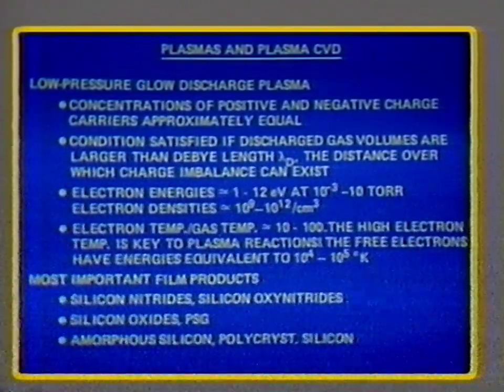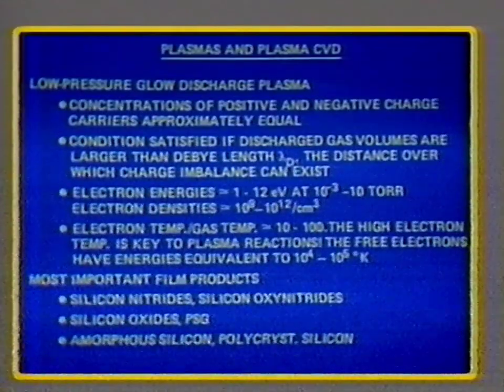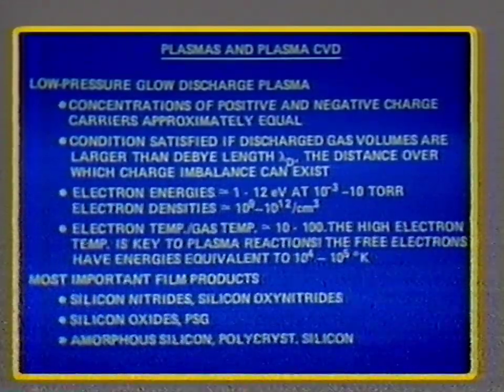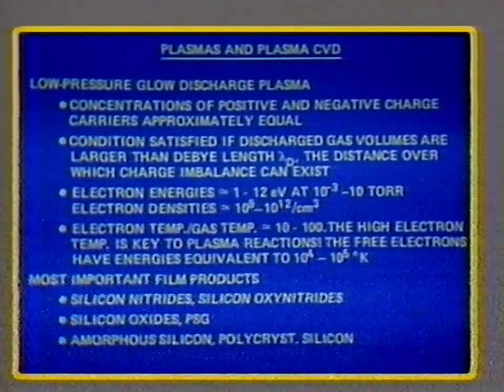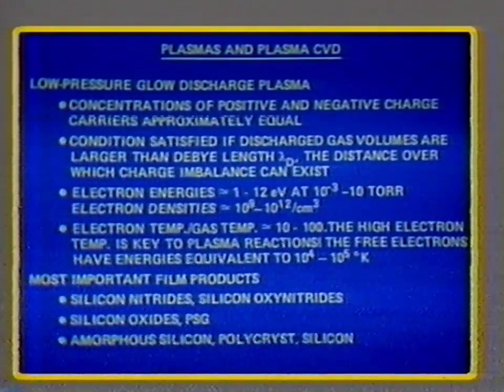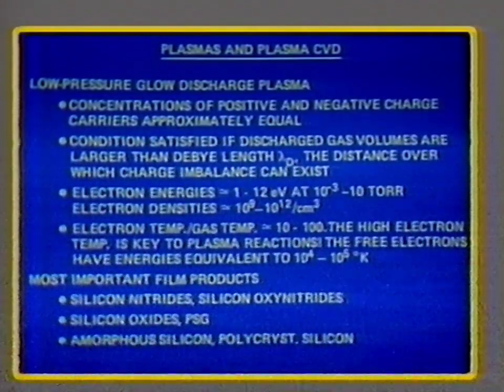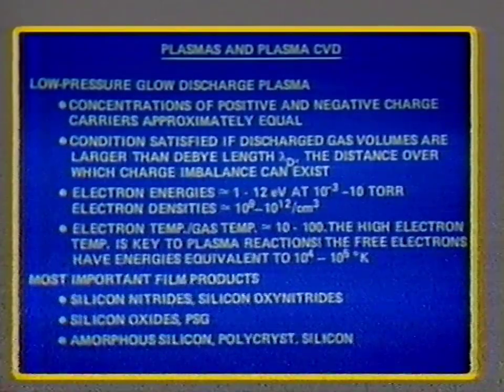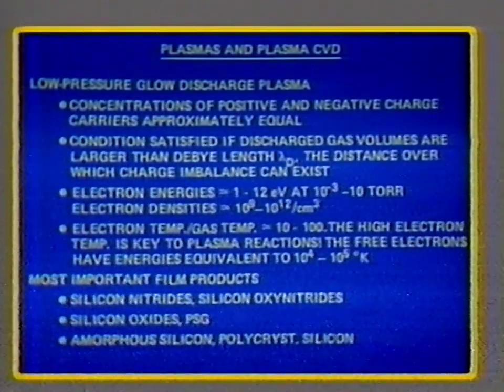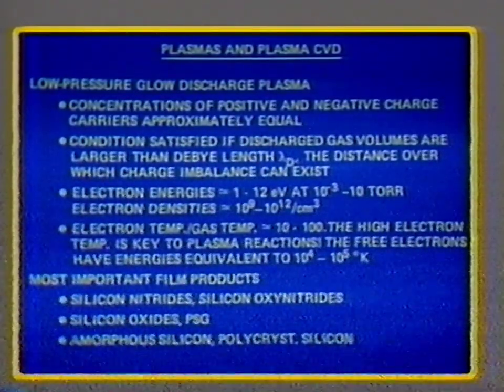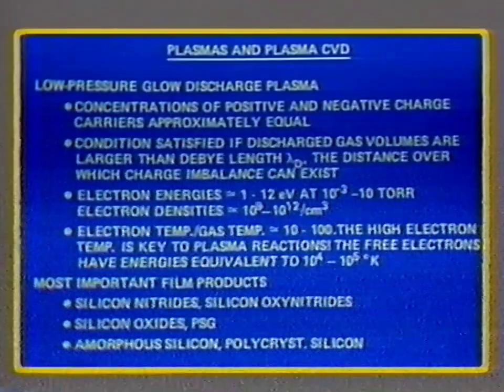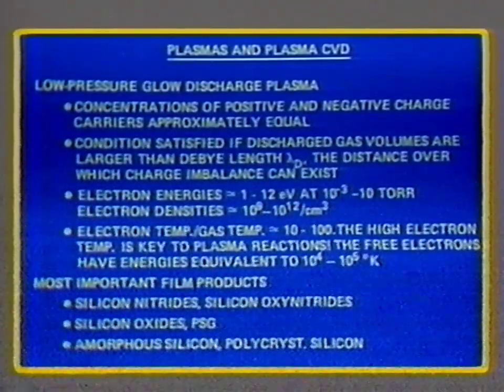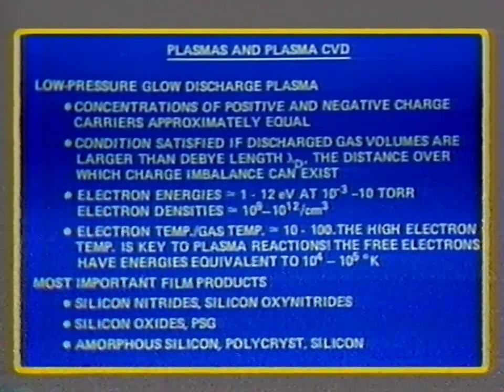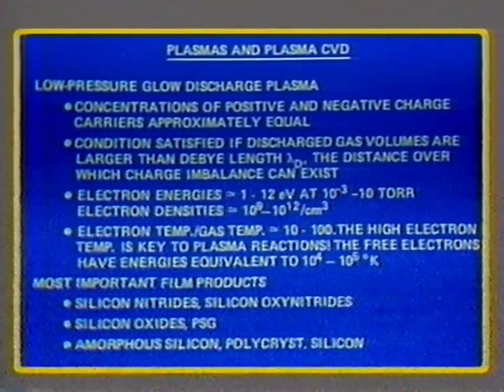Now, the high electron temperature is really the key to plasma reactions, and this is why we can deposit films at very low nominal temperatures of from room temperature up to a few hundred degrees C. Nevertheless, because of the very high electron temperatures available, we can produce films of very good quality. Now, the most important applications of plasma CVD is for the deposition of nitrides and oxide layers.